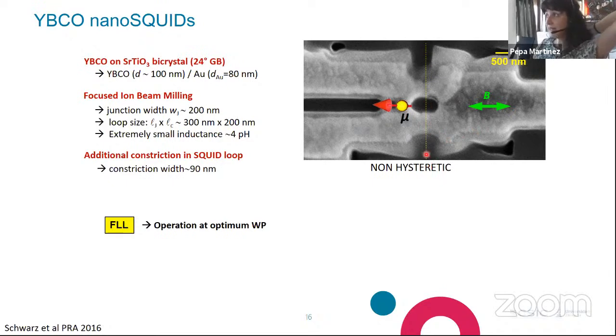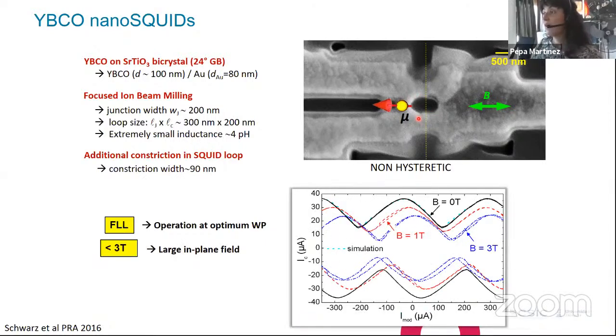Josephson junctions are here, lying perpendicular to the substrate, and an external magnetic field can be applied in parallel to the substrate, so as to influence our magnetic particle under study, but not coupling any flux to the loop, neither to the junctions. So, as I already said, these devices are able to work under the application of large fields. Here you see the modulation of the maximum critical current obtained at 0 Tesla and after the application of 1 and 3 Tesla. These fields are extremely large if you think you are working with a superconducting nanodevice. It's really a very, very large field, and still the modulation of the critical current is only slightly degraded.